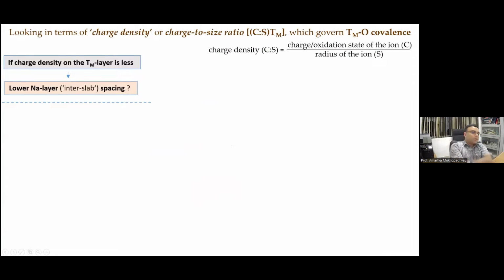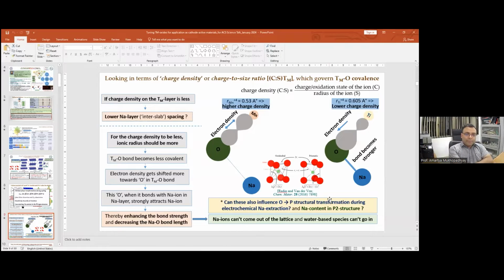Okay, fine. So first of all, the usage of NMP can be done away with if the active material is stable in water. In that case, we can use water as the medium for electrode preparation, and we don't need NMP. And usually the anode side is water stable, the hard carbon or graphitic carbon. So even now, most of the anode electrodes are made using water-based slurry. People are not trying to get away from NMP for the anode side.